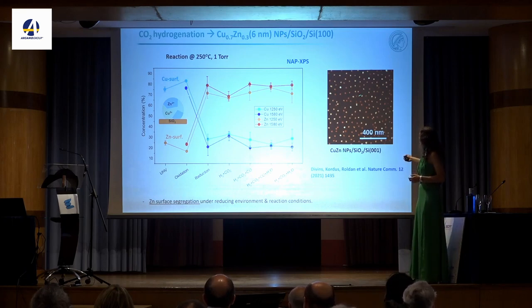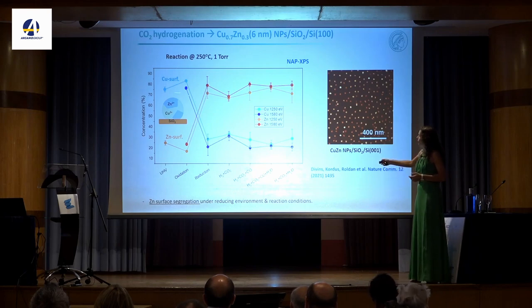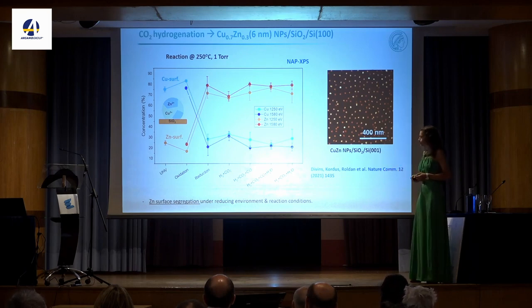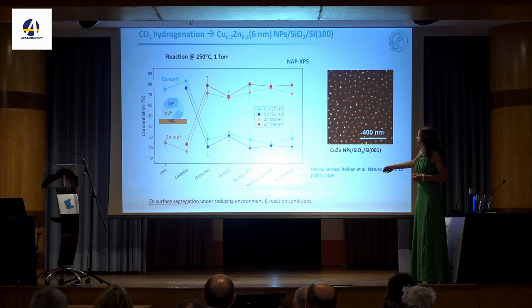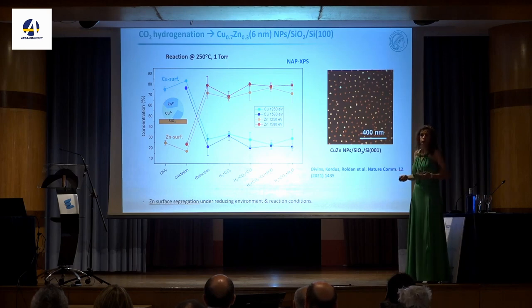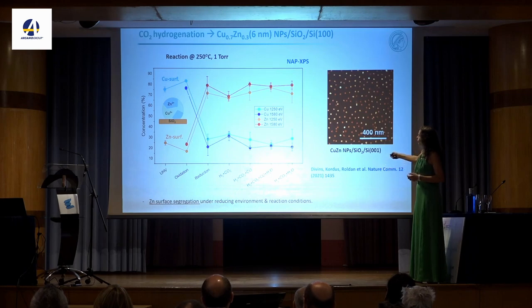So this is about 6 nanometer copper zinc particles on silica, and we start with about 75% copper, and then this is zinc. And now you go to different reaction environments. And you can see that when you go to the reaction conditions, either in hydrogen and CO2 or hydrogen, CO2, CO, and we also added some of the things that we are producing, water, to test if there was any difference, you can see that zinc oxide goes to the surface. So you get zinc at the surface, as zinc oxide, and you see the copper going subsurface.